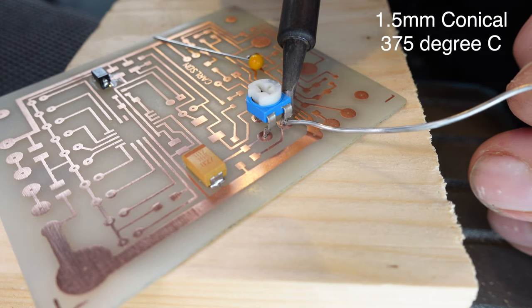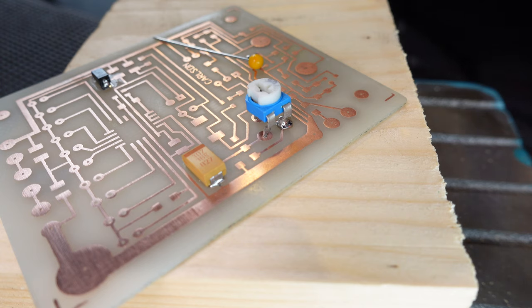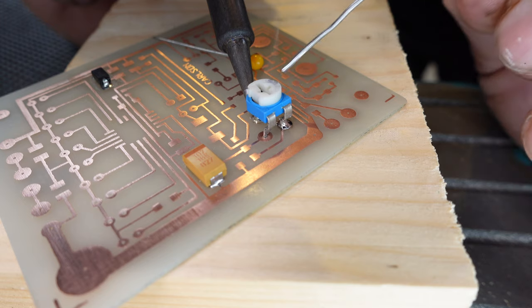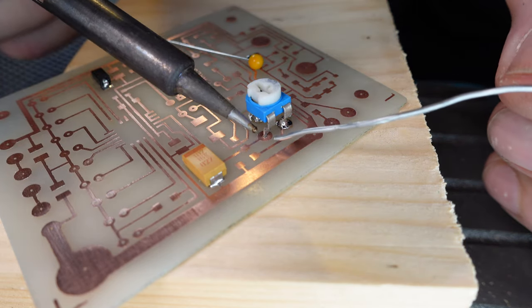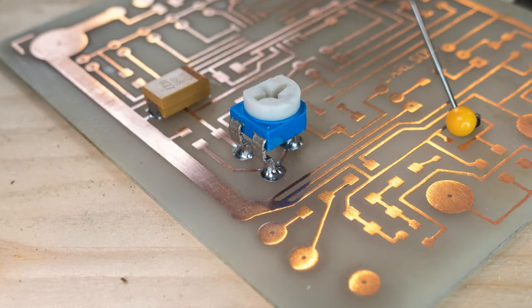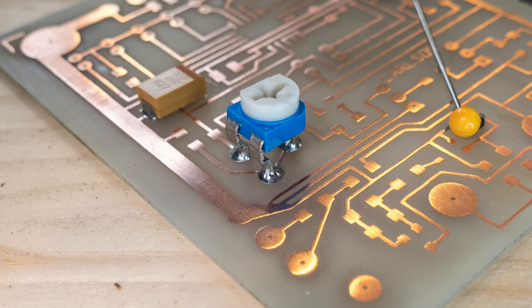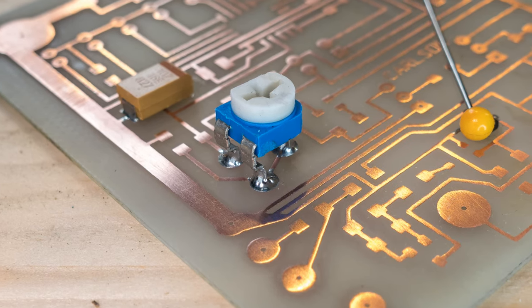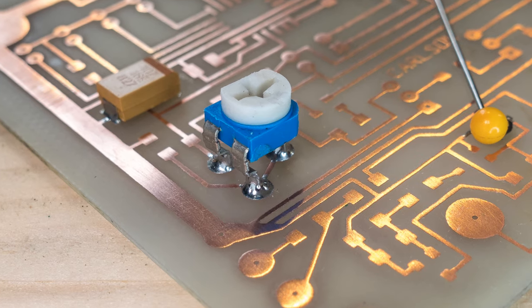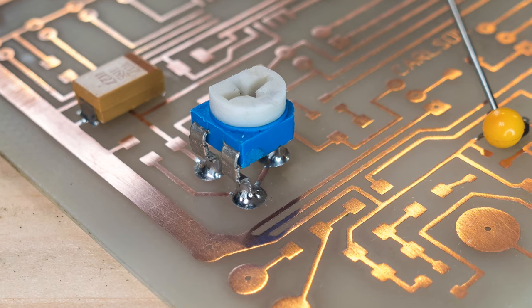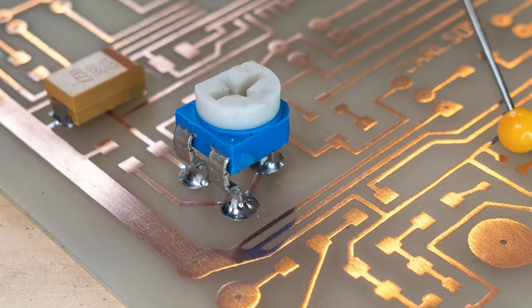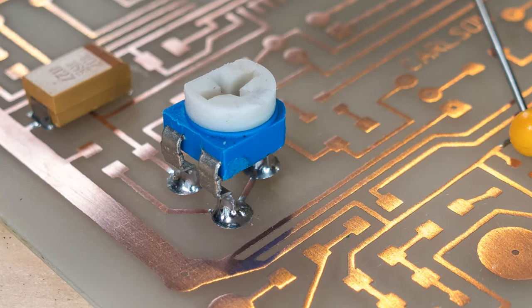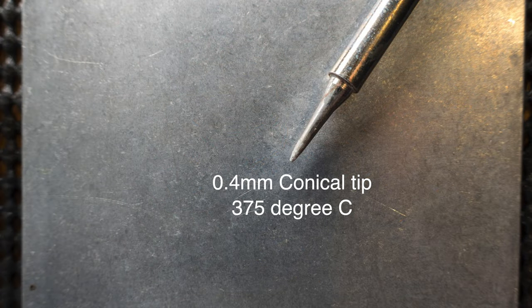This is 1.5 conical again, 375 degrees always with me. At 375 degrees you don't have to linger, it does the heating really quickly. That's my style, I prefer the iron quite hot so I don't have to hang around too long. Solder all small components on first, leave the big ones like the potentiometer till last. That means you've done the bulk of the rosin or flux cleaning beforehand. You don't want lots of liquid flying around your potentiometer. If it gets inside, a bit of thinners or isopropyl and rosin, it will knacker it.